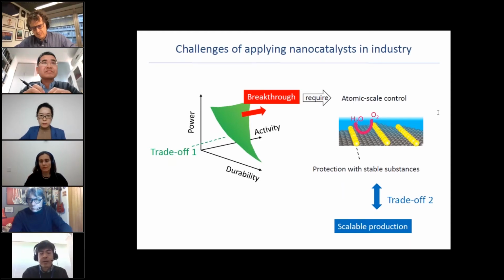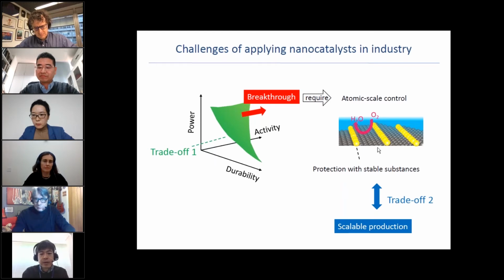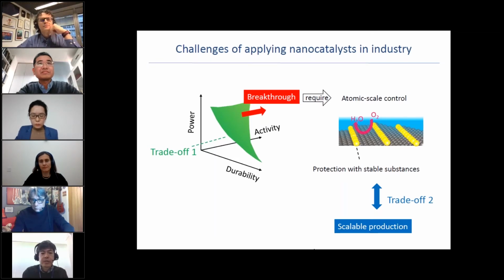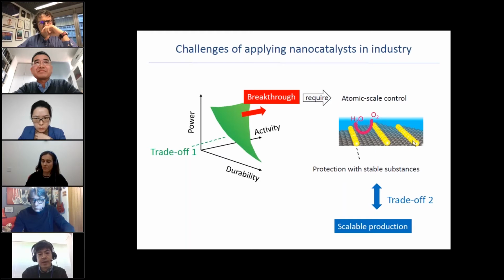So the requirement for high power densities in automobile applications, where the size of the stack is limited from the viewpoint of space, makes the development of ORR catalysts more challenging. In laboratories, many researchers developed nanocatalysts with surprisingly high activities, but I'm not going into the details of the technical background. It's known that not only the activity per catalyst amount, I mean the platinum mass, but also the surface area of the catalyst per platinum mass is needed for improving the durability and the power density.